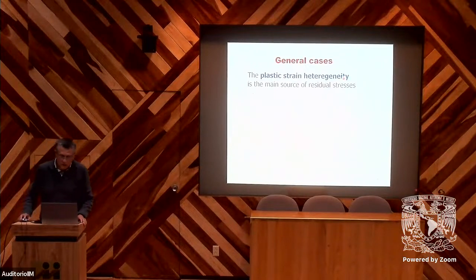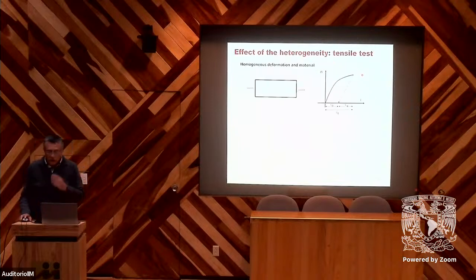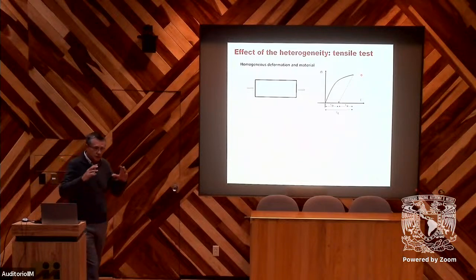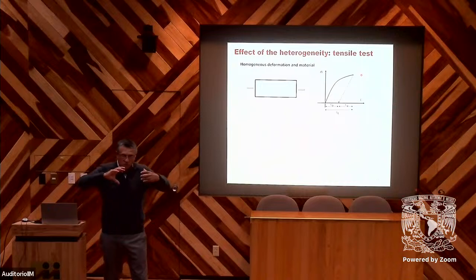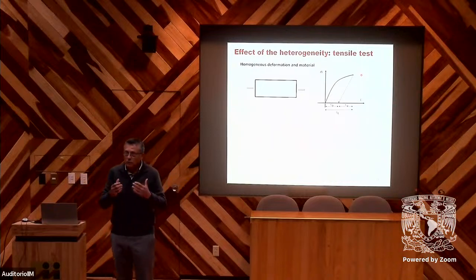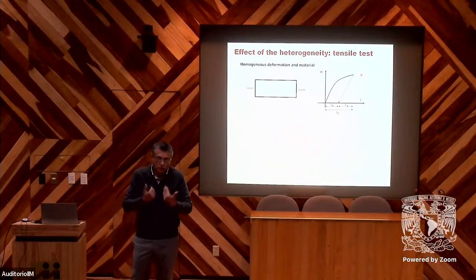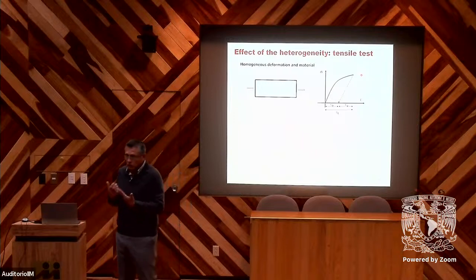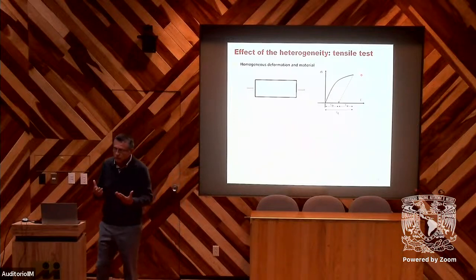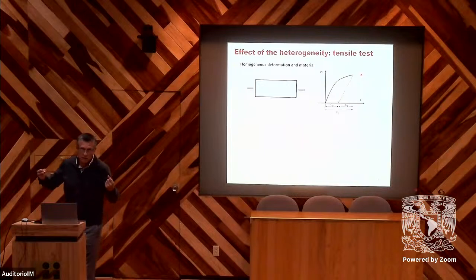So we can say that in the general cases, the main source of residual stresses is the plastic strain heterogeneity. So now let's consider this heterogeneity. That means if you have some loading, for example, by torsion, by bending, you have heterogeneous deformation. So the case where you don't have this heterogeneity is the tensile test.